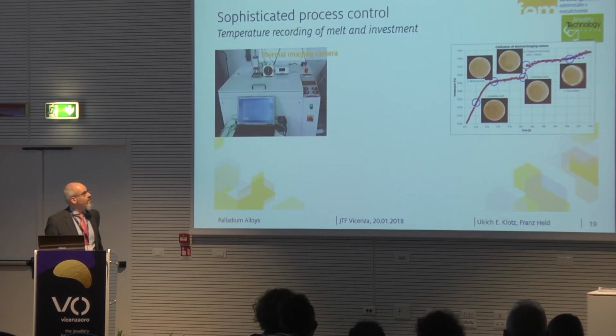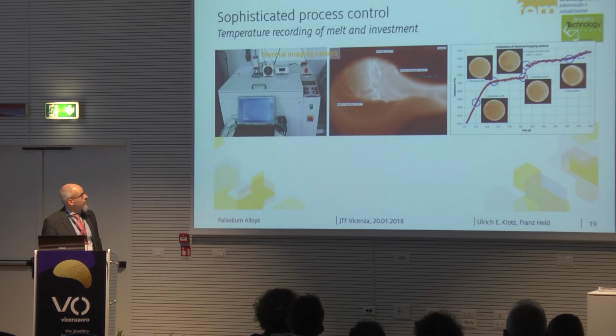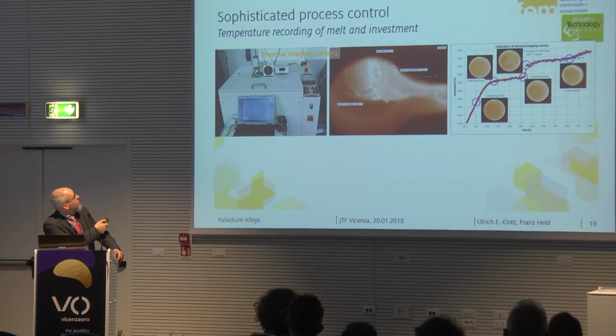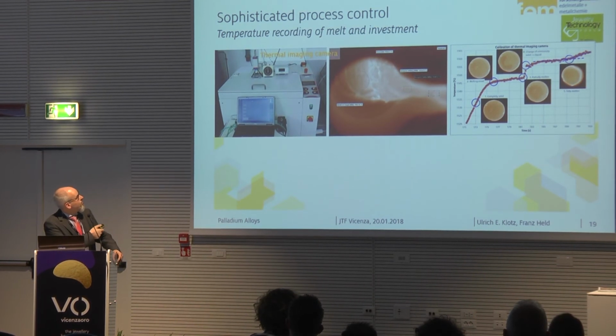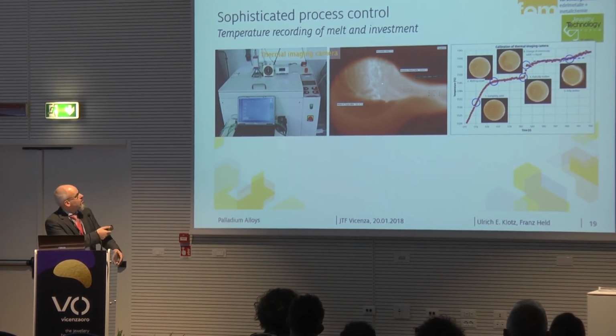Now, when we do the process, we have to take care of the process control, and therefore we work with a standard casting machine, but we have some sophisticated characterization methods in line during the process. So for instance, we have a thermal imaging camera which is mounted here and has a view on the melt. This is a typical image at the moment where the melt flows out of the crucible. So we can record the temperature very precisely, and we can identify different situations.